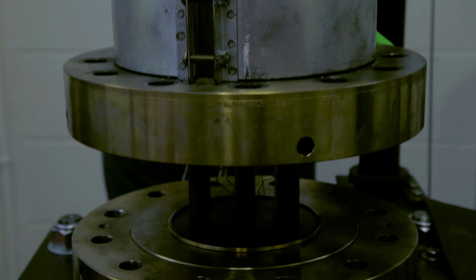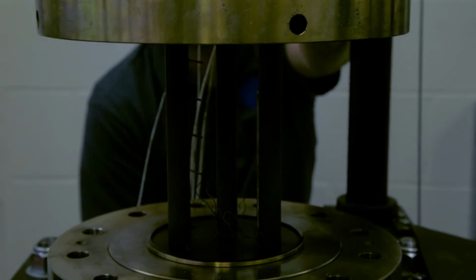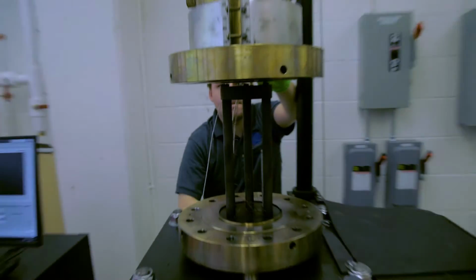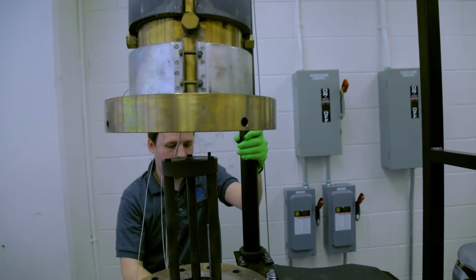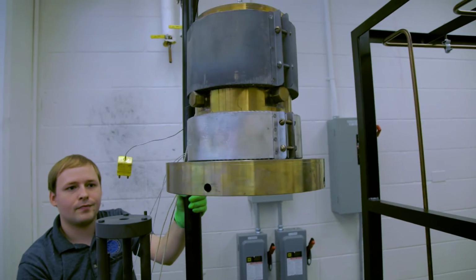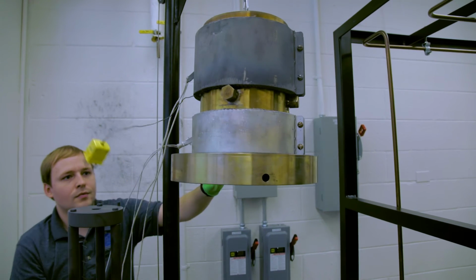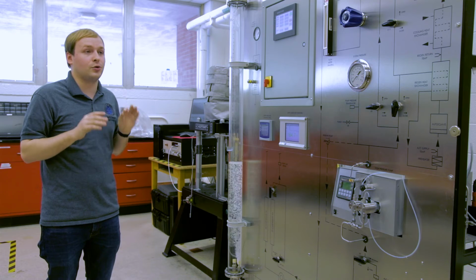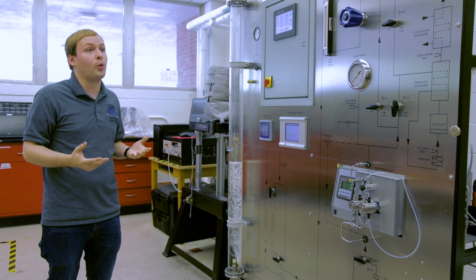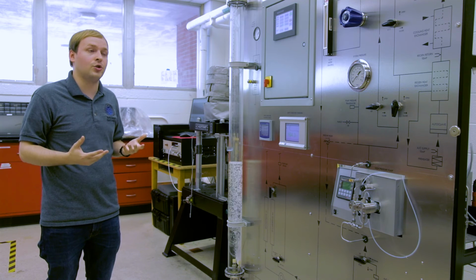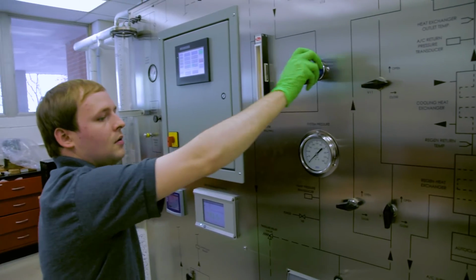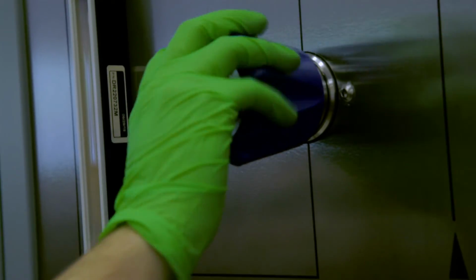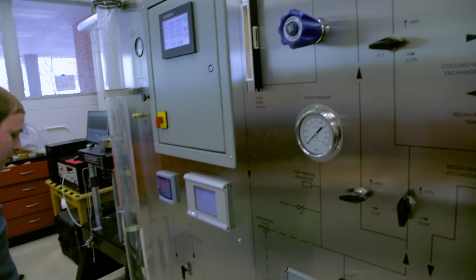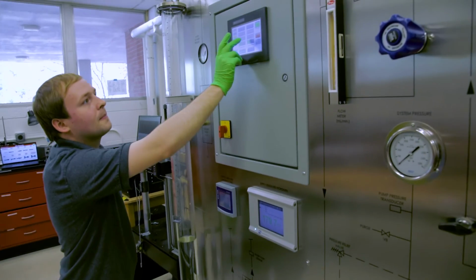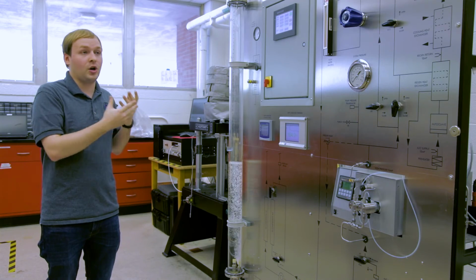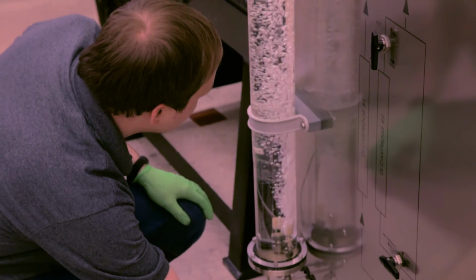One of the projects associated with this is known as the silicon carbide project. Ever since Fukushima happened, we are always looking for accident-tolerant cladding. And one of the cladding candidates that we have is silicon carbide. The problem with silicon carbide is that it corrodes a little faster than we like in boiling water conditions. So what we're looking to do is add a coating, either by physical vapor deposition or chemical vapor deposition, such as titanium nitride or zirconium nitride. And that project is just looking to see how fast our material corrodes and if we can improve it.